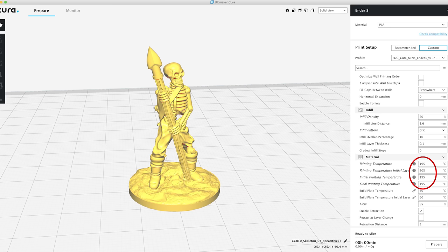Now, if you're printing with Hatchbox, I've cranked my Hatchbox miniatures down to 190 or in even some cases 185 and had good results with it. But again, I'm using eSun PLA Pro here, so 195 is about as low as I can get it. Now, why do you want it low? Well, it goes back to that radiant heat issue. The lower you can keep the temperature of the nozzle, the less radiant heat there is and the less chance you're going to have of causing lower layers to hit that glass transition point. So, keeping it low also allows the part cooling fans to cool it faster and get it to harden faster to maintain sharp detailing.